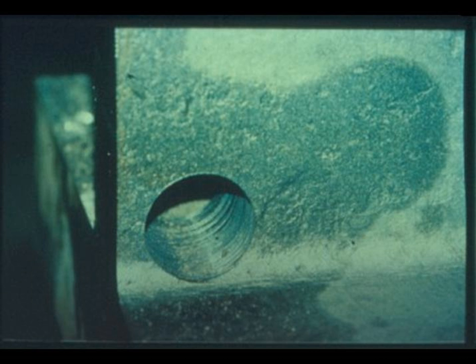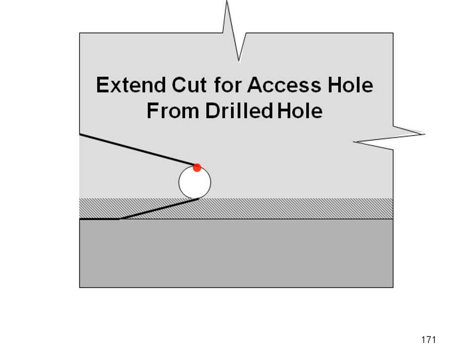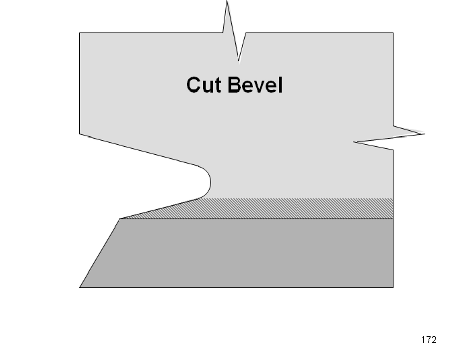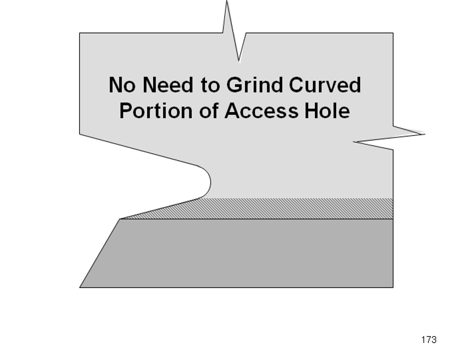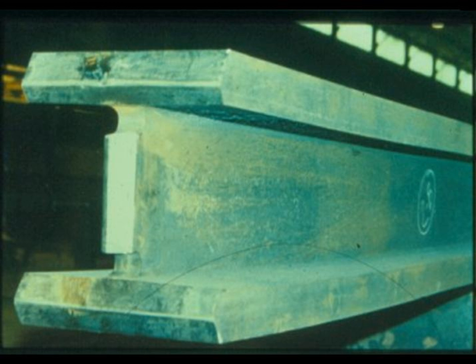Now after you drill the hole, it's a simple matter of extending that by flame cutting, removing that material, and now you don't need to grind the radius region. You can use your 9-inch grinder to grind these flats, and that's pretty easy to do. It was the radius region that was the problematic area. It was the radius where grinding was hard to perform. Now again, this is a very old shape, but you see nicely prepared weld access holes. You see nicely prepared bevels, and this has been prepared to receive the groove welds that we're going to have later on.